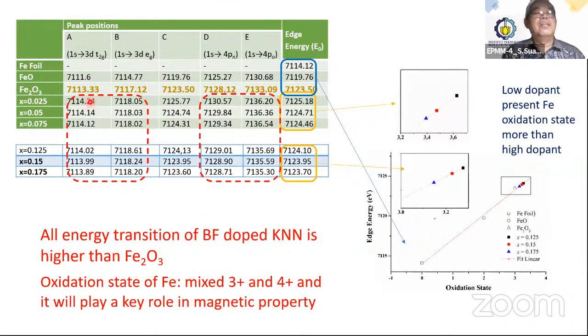All energies fitted for our samples are higher than those of ferric oxide. For the analysis, by taking the edge energy of iron foil, ferrous oxide, and ferric oxide and plotting it against oxidation state, we can estimate the oxidation state of iron in our samples. It seems here that for low dopant content the oxidation state is higher than that of high dopant content. Therefore, we conclude that the oxidation state of iron in our samples is a mix of 3+ and 4+, and it will play a key role in the magnetic property.